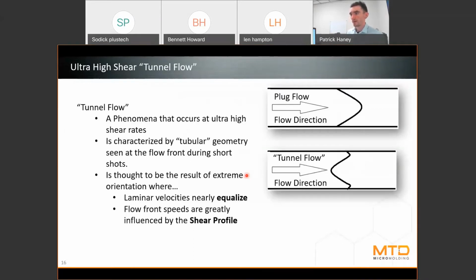Okay, so when we experience ultra high shear rates, when we take these flow channels and we make them super small, like in our molds and even the part geometries that we make, that frictional drag that is experienced through shear rate tends to skyrocket, goes very, very high. Now, typically, like I said earlier, in non-Newtonian fluids, the harder you push them, the easier they flow for the principles we've talked about. And when that occurs, you'll get something that sometimes we call plug flow that is loosely represented by this top picture here, right? Because of that fountain flow dynamic.